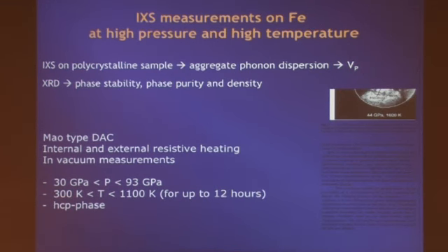We can use inelastic X-ray scattering, again on a polycrystalline sample, so what is probed is the aggregate phonon dispersion and directly VP, and in parallel, X-ray diffraction measurement to check stability, phase purity, and density. In this kind of experiment, given the need of a long exposure time and of a stable, uniform heating, heating has been done by resistive heating, either putting a micro-machined furnace just around the anvils, or directly applying a DC voltage on the iron sample. Through platinum leads, we are bringing current to the sample that is heated by ohmic effect. Results have been collected in the 30 to 93 GPa range, 300 to 1100 K, all in the hcp phase.